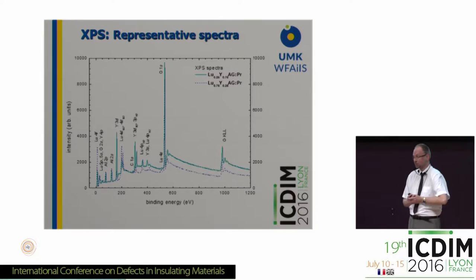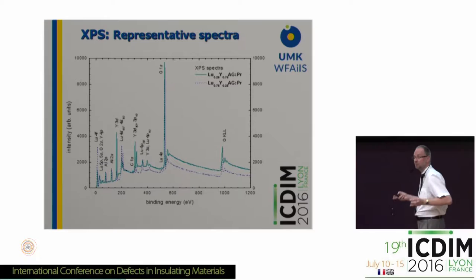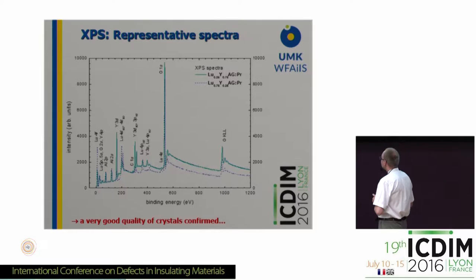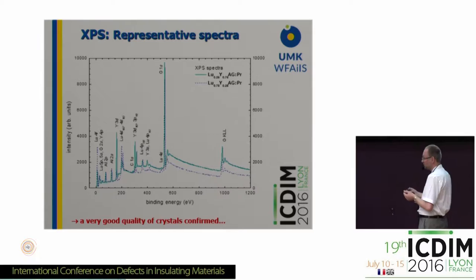Now let's take a look at what's inside the crystals. Here I show some representative spectra of X-ray photoelectron spectroscopy. We have very clear, nicely resolved lines which can be attributed only to the constituents of the crystals. There is only one line that doesn't belong to any of the crystal components, but this is the well-known carbon line which enables calibration of the spectra. Based on the XPS studies, we can conclude that the crystals have very nice structure — they are very clean — and everything works well in our series of growth of the mixed crystals by the Czochralski method.